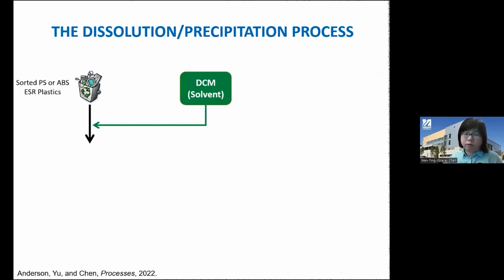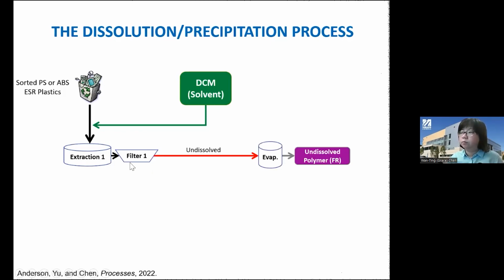So we use these dissolution-precipitation processes. The way we use it is, first, we identify a solvent. It could be DCM, dichloromethane, or another kind of solvent. First, we dissolve the targeted polymer, such as polystyrene or polycarbonate. And then we can remove the undissolved one.